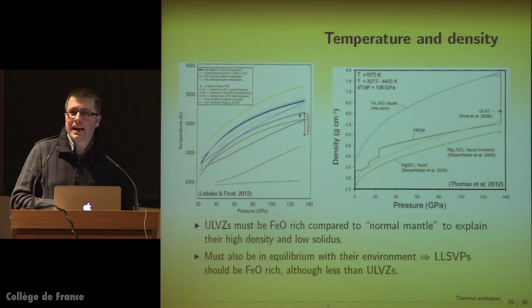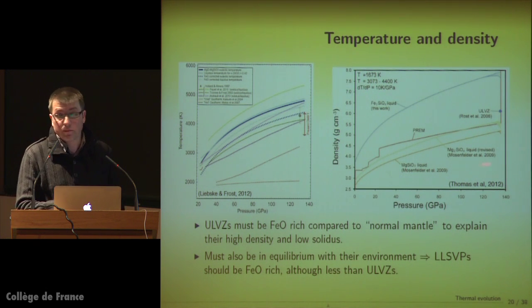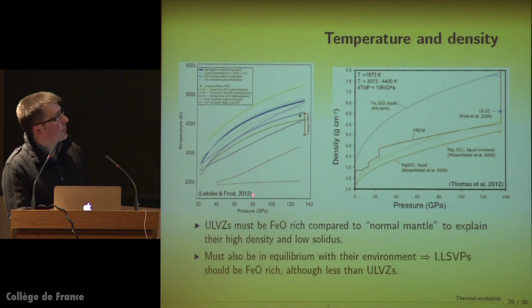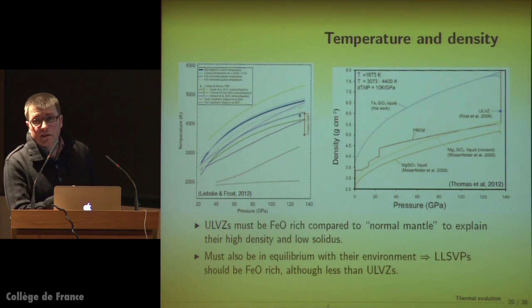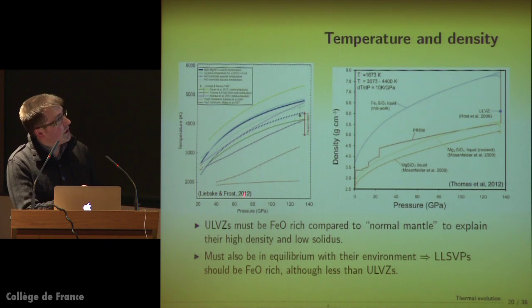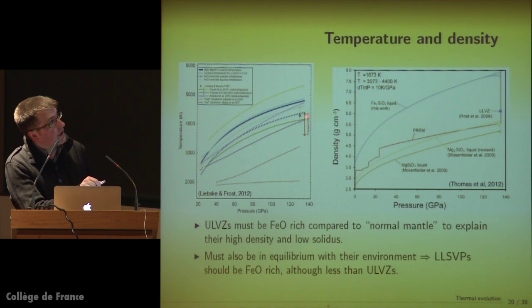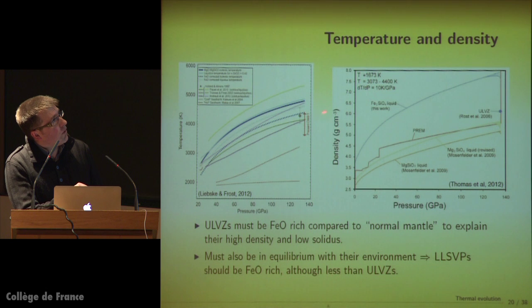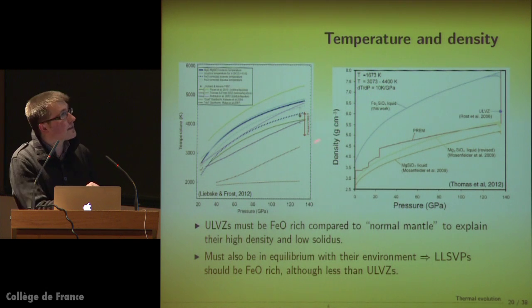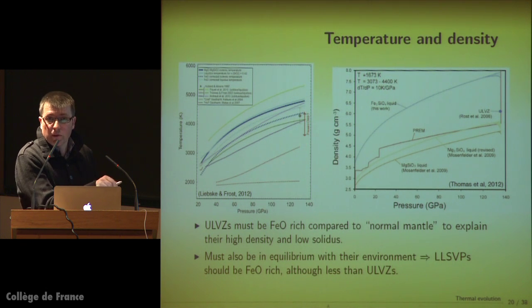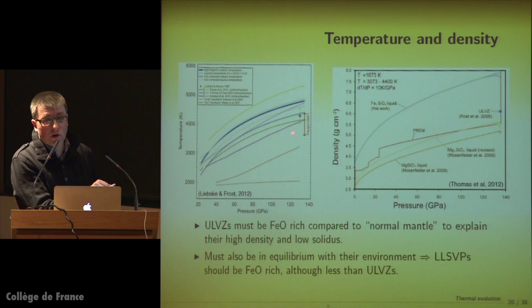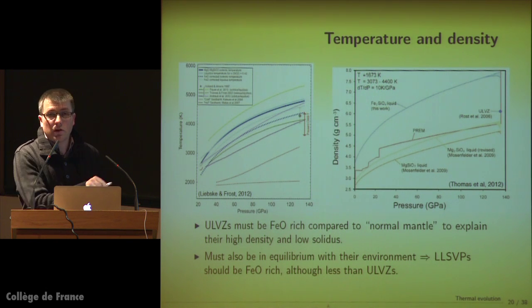So we also want to match the density and look at what the temperature should be there. These are from two recent papers. This is a comparison of the different melting temperatures, liquidus and solidus, that have been reported in the literature, compared to the present-time CMB temperature range that is in this row here. What you take from this kind of plot is that to have liquid or partial melt at the CMB at present time, you need to be at the top of this range, or you need to change the composition and put more iron in this region to decrease that temperature to lower values.